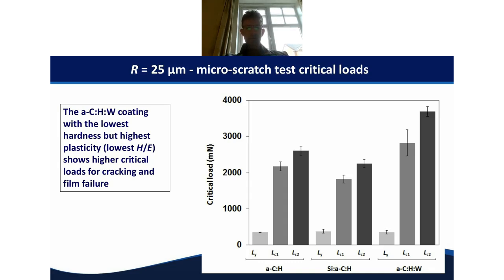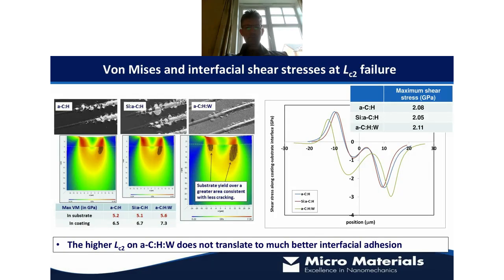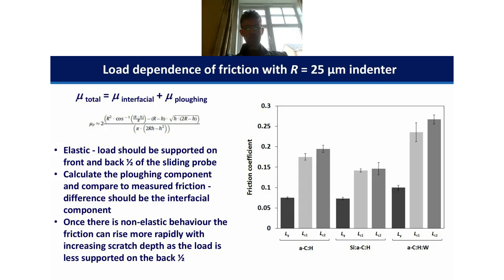If we look now at critical loads at failure, what we can see is that this soft system, this tungsten doped system, actually has much higher critical loads at LC1 and LC2. And we can look at interfacial shear stresses as well. When we do that, despite these differences in LC2, when we actually do the calculations within the SIO software, we see the stresses at the interface are really relatively similar. So that suggests that it's the mechanical properties of the systems that are giving the apparent differences in adhesion, as opposed to a true interfacial difference between these coating systems.